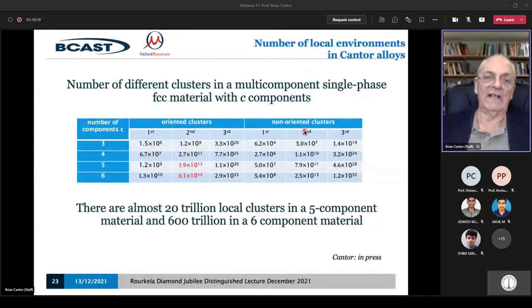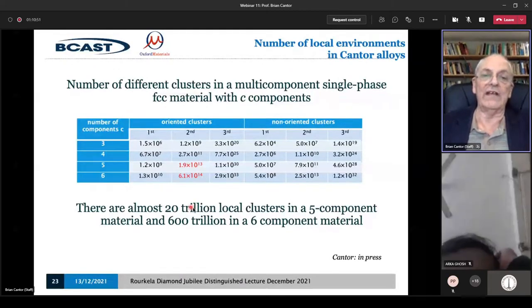So first of all, let's look at the number of these different clusters, as we can call them, of atoms with their first and second near neighbors. If we take first and second near neighbors and take a 5-component system, it turns out there's this number, just under 20 trillion different local clusters. It's an enormous number. It's because in the face-centered cubic structure, the number of first and second near neighbors is a total of 19 different atoms. It's a lot of different atoms. And the number of ways you can have that with 5 components is 20 trillion.